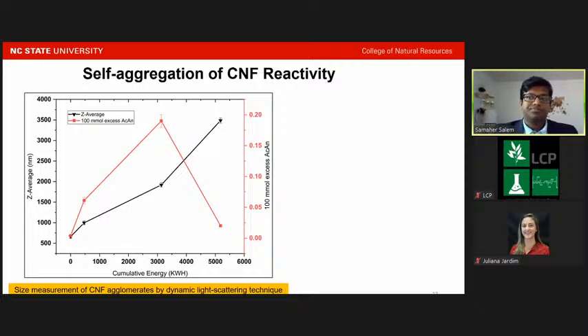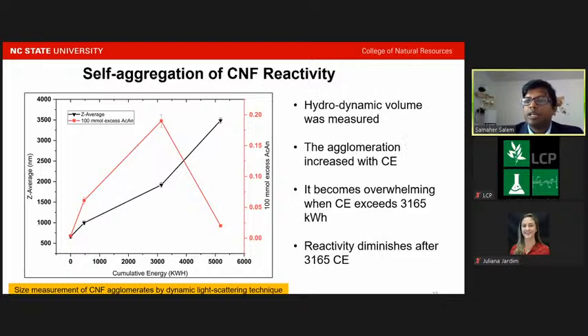Further, we also investigated the self-aggregation due to formation of hydrogen bonds between the hydroxyl groups of the nanofibril samples by size measurement of different nanocellulose samples by dynamic light scattering. And we could find that the diameter of the CNF agglomerates in the suspension increased with the increase in energy. The increase was significantly high after reaching 3000 kilowatt hour per ton energy, which explains why the degree of substitution went down drastically when higher energy was applied beyond this energy.